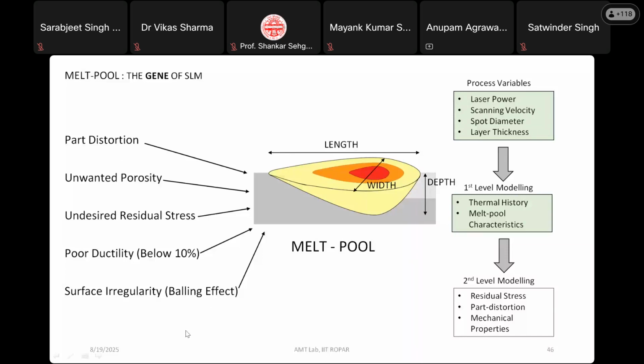There is a typical defect, the balling defect, in most of the SLM-based or LPBF-based processes. The process parameters which control this are laser power, scanning velocity, spot diameter and layer thickness. So a set of modeling, first level modeling, second level modeling, was done in order to predict the melt pool dimensions for a given set of variables and then optimize it. In a nutshell, this is something we attempted before deciding what kind of input parameters we should have for 3D printing using SLM for our chosen biomaterials.